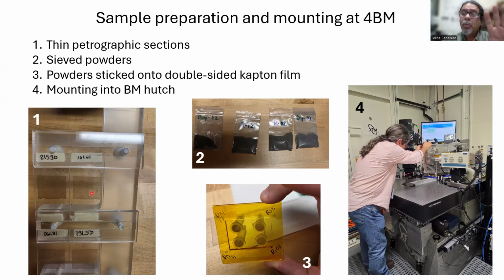So we can do maps in different sections of these thin layers and observe individual particles that can be individually analyzed chemically and structurally. Also, we brought some of the sieved powders to the synchrotron and dispersed the powder on top of a Kapton tape, so they can be analyzed without being ground as the petrographic sections were. And this is the mounting of the samples in this rack that will be illuminated by the beam that comes from here. This is the X-ray detector, and there is a microscope camera here, which selects the regions where we are going to study the particles.